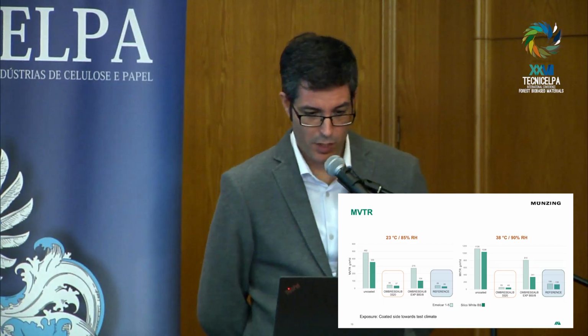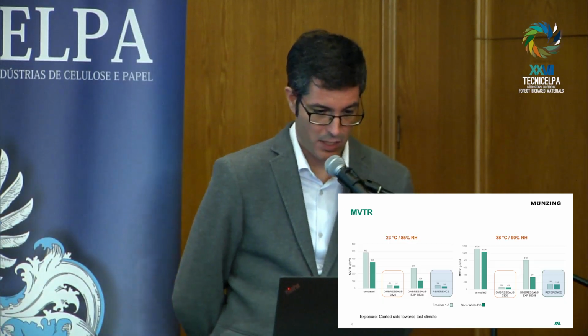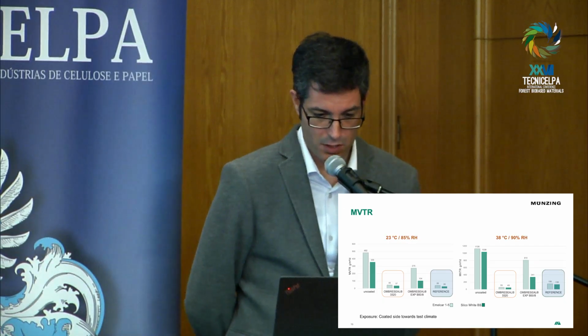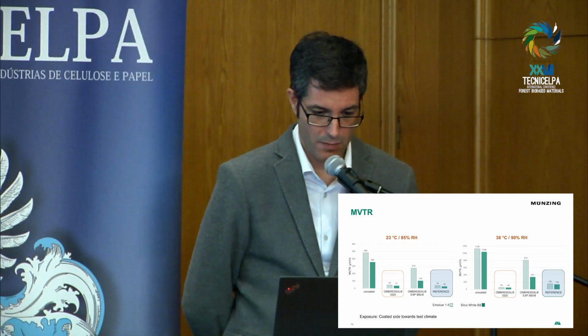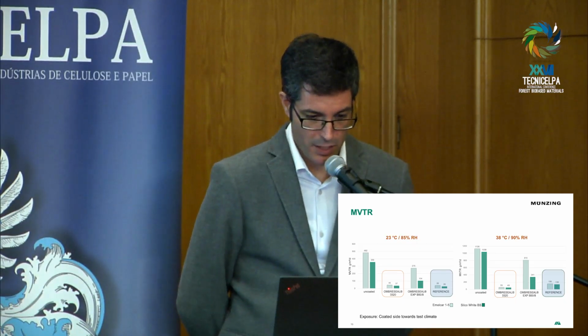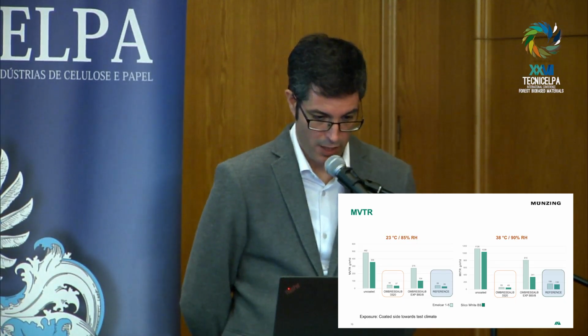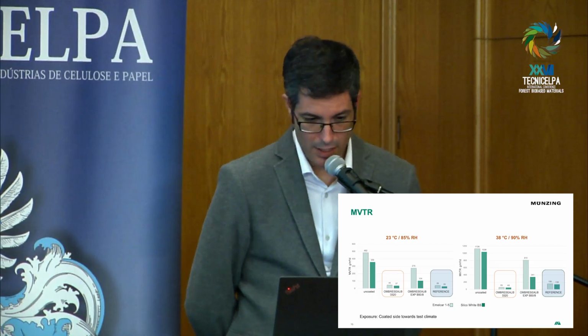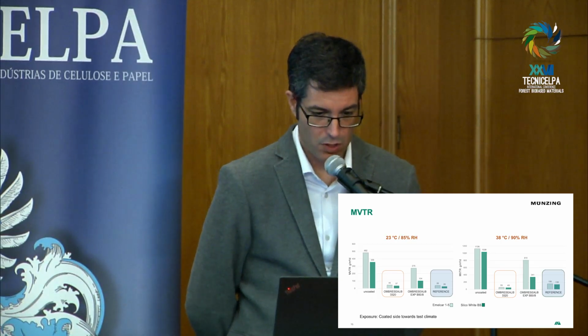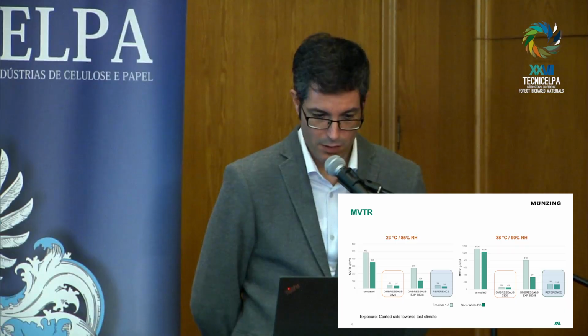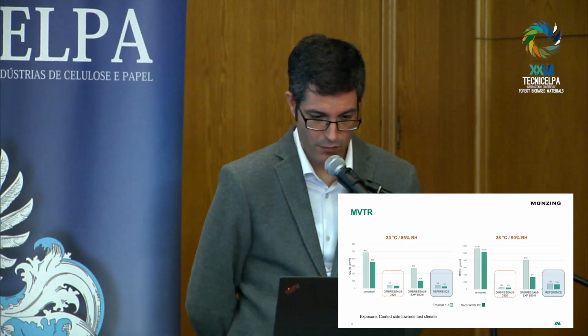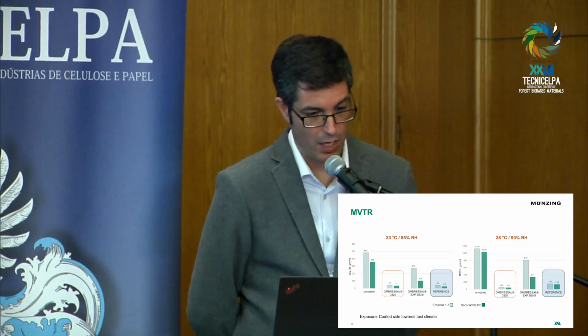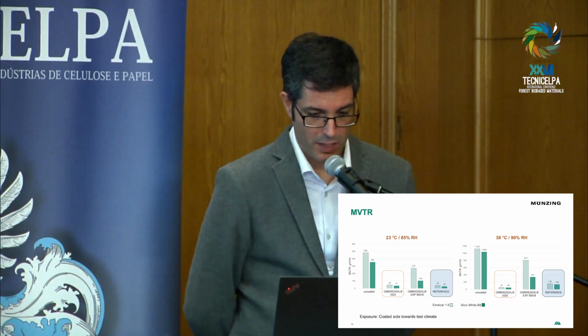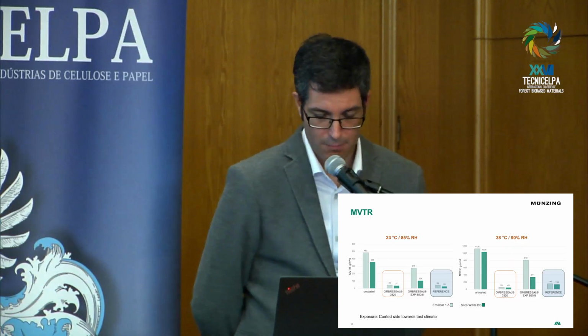That's why we also test the reference, and you can see here a big improvement, which is also expected with the fossil-based material. But the Ombrasil 3320 is not far away. If you look at the MVTR values, we are talking about 6 in terms of difference, and in the Silco, the difference is also not so high. It's only 11 grams per square meter a day, so it's a good result.